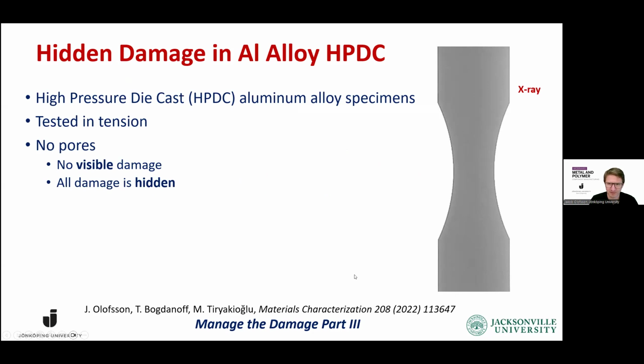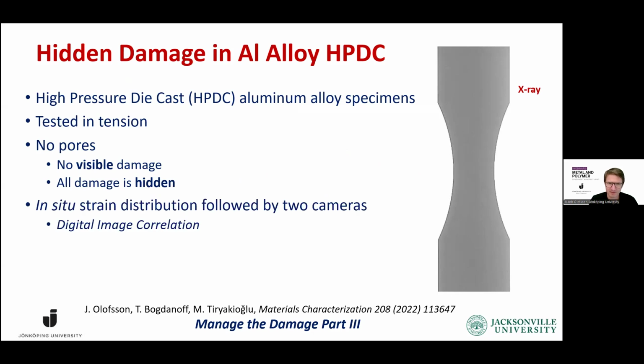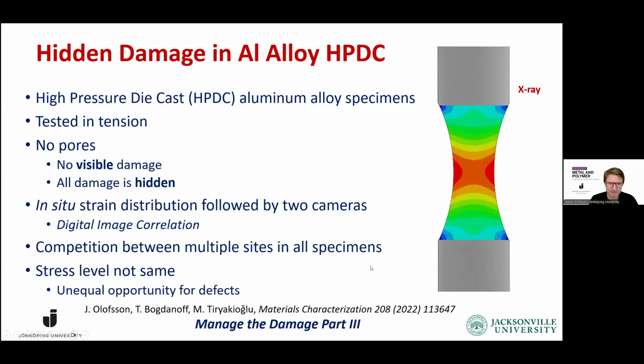Instead, these are samples that were actually originally intended for bending fatigue testing. But we had an idea to test this in tension because we were looking at using a technique called the virtual fields method to develop a constitutive model that describes the elastoplastic behavior of this material, capturing a larger variation of stresses than just purely tension load. But we tested this. If you test this in tension, you will create an uneven strain field. And as we said, there is no visible damage in these samples. So all damage that we see is then, as Turas introduced, hidden damage.